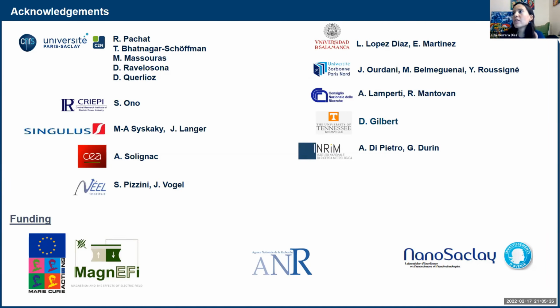So it might not be as easy to get to the first one and the second one, depending on what you have in between. But regarding the asymmetry itself, I don't think that would affect this in any way. Another thing that could affect the process is to have materials like platinum, which people use for hydrogen storage, for example. So some of these ionic processes could happen with protons. You could expect the ions to be a lot more concentrated in the platinum layer, simply because it's this material that really captures hydrogen, and it's not the same in the top layer. So this could also give you another asymmetry. But the asymmetry itself having an effect on the ionics, I see it only from the point of view of the ions traveling through different types of materials.